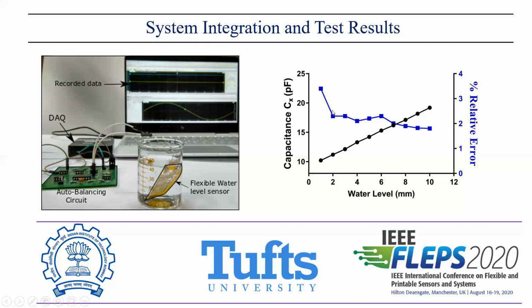The maximum is around 4%, but if we look very carefully, for water levels from 2 mm to 10 mm, it varies within plus or minus 1% of relative error. So the system actually provides very accurate information thanks to the auto balancing circuit and the fabricated sensor.